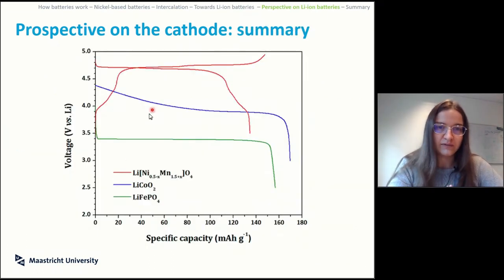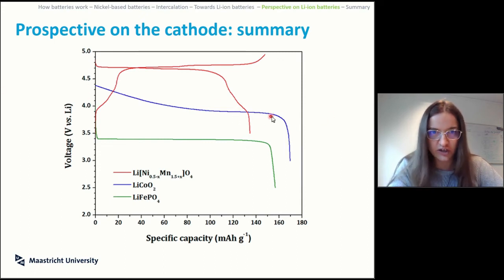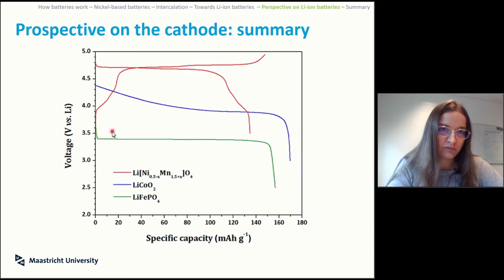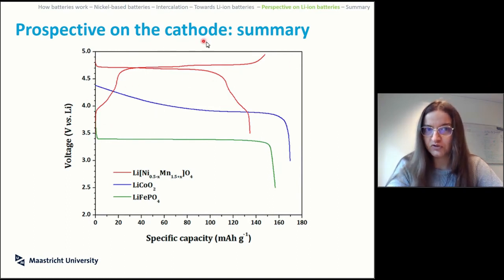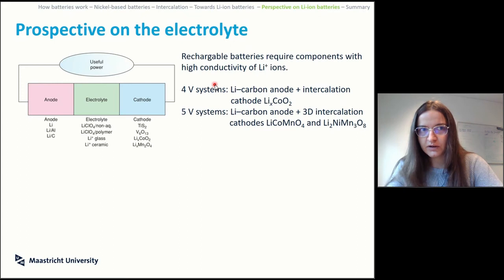So, summary of what we have on the cathodes. This one is the one that is usually used. The lithium cobalt oxide is the one that you find in most batteries, which can stay basically between 4 and 4.5 volts, charging, discharging completely, and no one cares. Nice. Then you have the one that we just saw, which is the olivine, which is a lower voltage but perfectly stable, perfectly flat, amazing. Then you have the spinel that, depending on whether you are using nickel to substitute it or not, you will end up with voltage drops, or you will stay stable at the right voltage with the known issue that we already discussed.